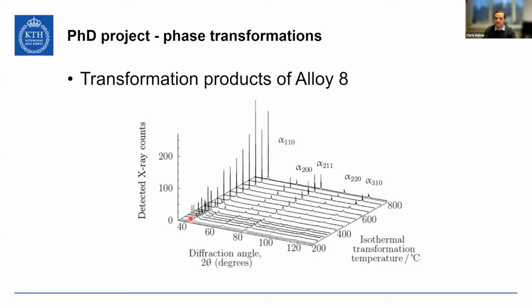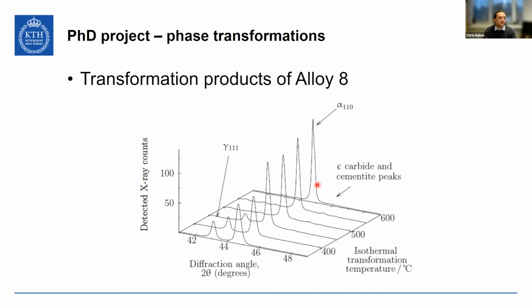And if we zoom in a bit closer, we can see how, as we lower the transformation temperature, we begin to retain more austenite following the completion of the transformation, exactly as one would expect for bainite. But that was just an interesting aside. The whole point was to make something which would form this nanostructured bainite, superbainite, and be thermally stable. And this is what we used the synchrotron experiments for.